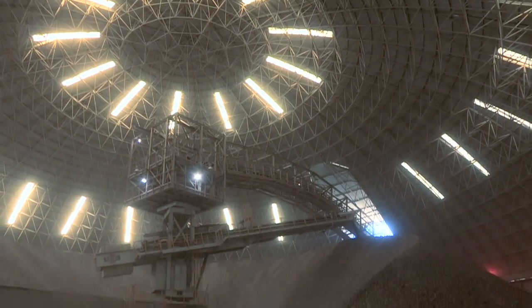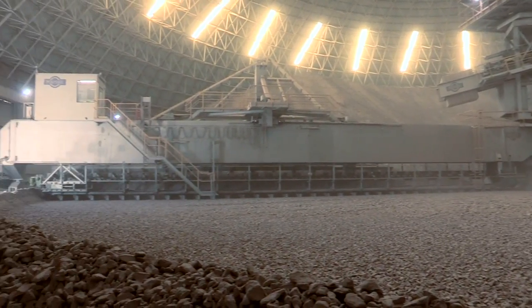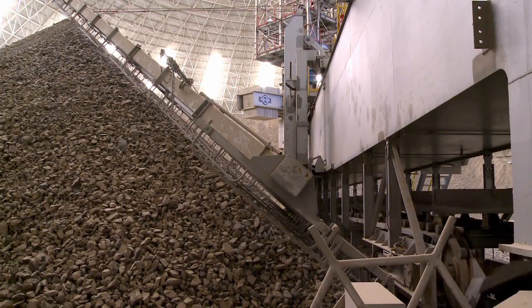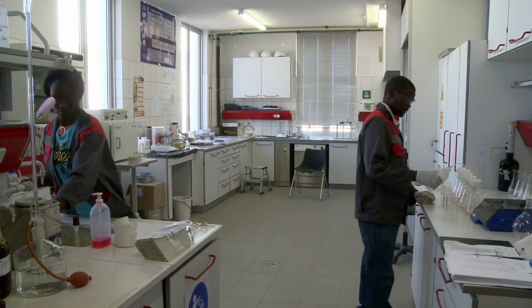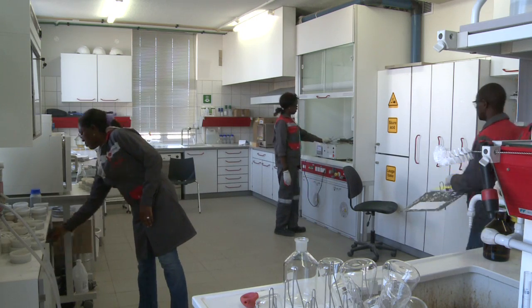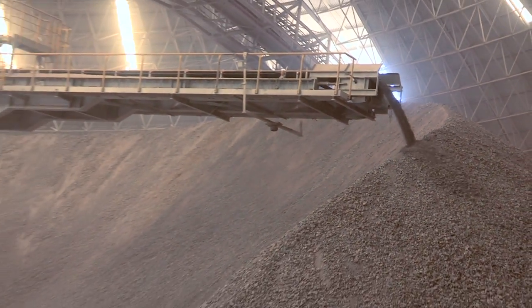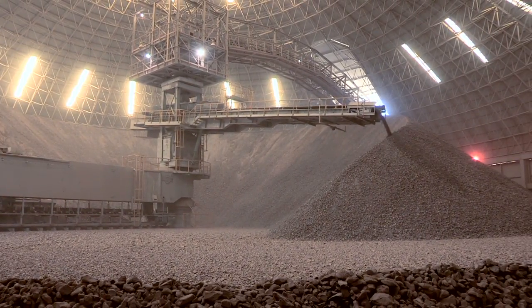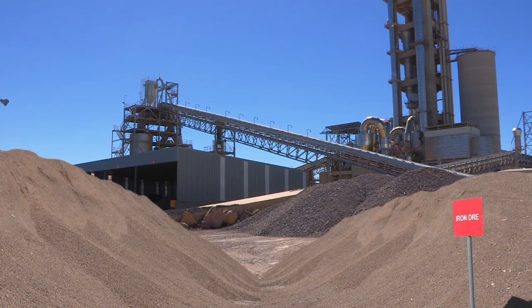The homogenization store has a radius of 81 meters and a height of 28 meters, and has a blending bed which can handle 25,000 tons of mixed materials. The chemical composition of the material is carefully monitored to ensure that it contains the correct proportions of limestone, shale and marl. A combination of materials is added to the mixture if the proportions differ from those specified by the quality department. Essential additives such as quartz and iron ore are added to the homogenized limestone, shale and marl material.